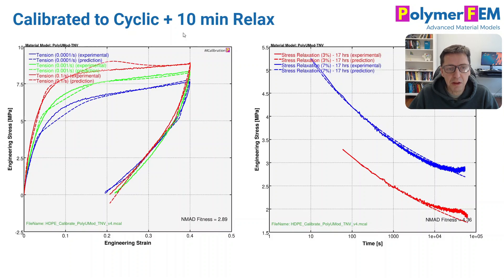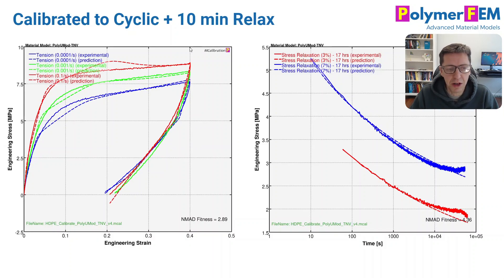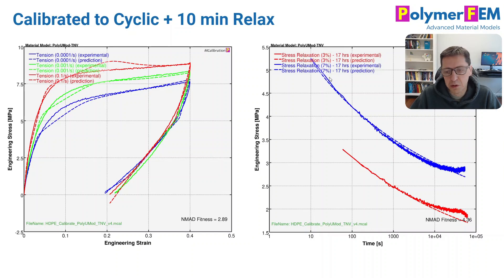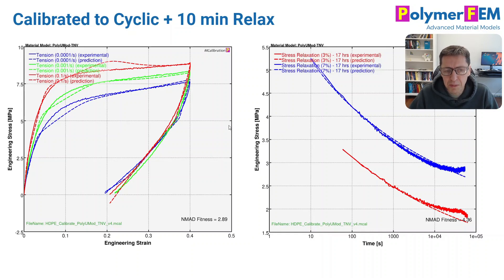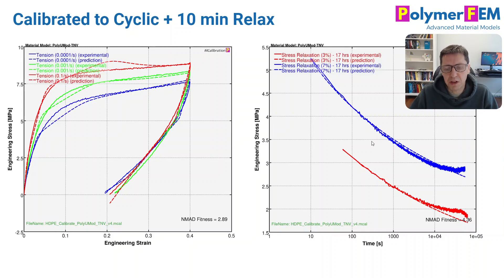Having a short-term relaxation test allows the model to be better calibrated to the complete data set. What if I change one minute to 10 minutes? The results look a little bit odd in the cyclic data, as the solver selected those parameters to better match the relaxation curves. Overall, it's a similar fit, but not necessarily much better — the relaxation curves match slightly better, but the cyclic data is perhaps a little bit worse.